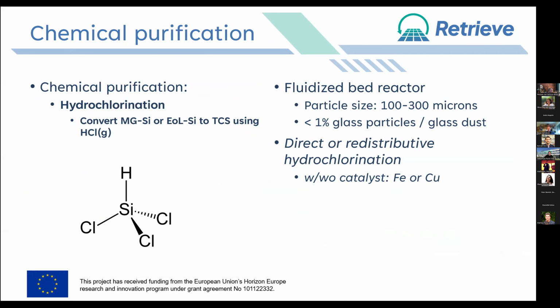And that leaves the conventional way, chemical purification. Well, this is the process we usually call the Siemens process. It's a bit more involved. It starts with the hydrochlorination, just converting metallurgical grade silicon, or in our case, end-of-life silicon, to trichlorosilane using hydrochloric gas. Typically in a fluidized bed reactor, starting with tiny particles. So it could be ideal for starting with crushed silicon from a module. And there are several different options to choose from here. So it could be a separate presentation to go through all the options here.